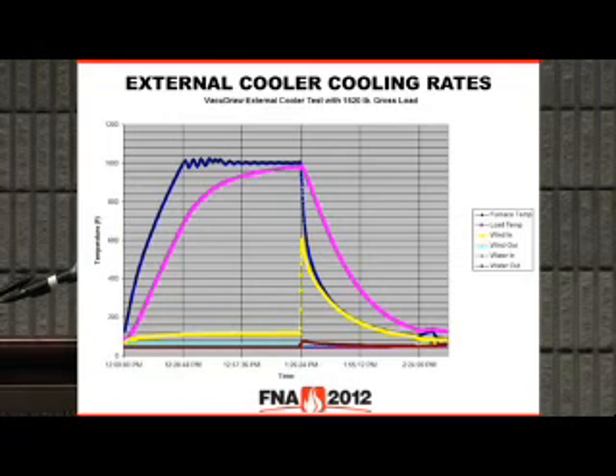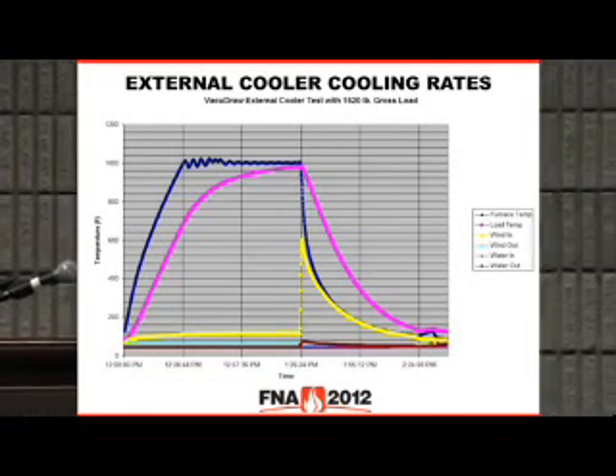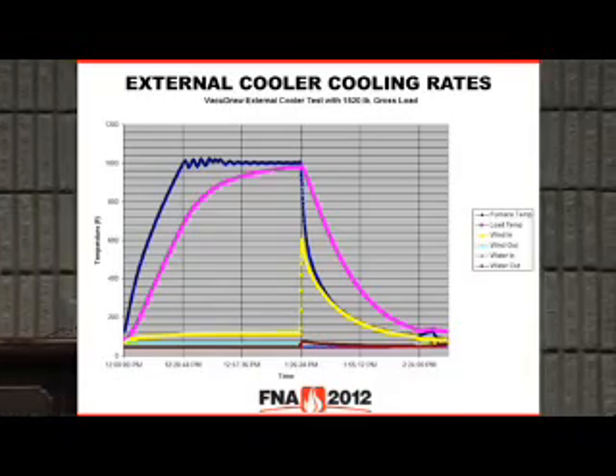The load, on the other hand, is taking a little bit longer naturally, and it looks like here's about 120 degrees. So up in this area here would be your 150 roughly. So you're looking at approximately an hour to bring a 1,500-pound load down to 150. So that'll give you a feel for cycle times and cooling rates.